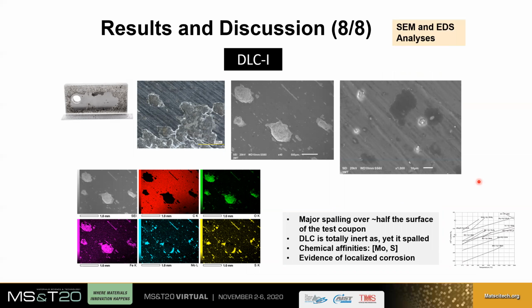Now let's look at the DLC coating. Remember, based on the general overview seen a few slides ago, this is where we had some of the worst corrosion rates. So what do we see? Here's a coupon. We see that this coupon does not look black, which is the normal color of DLC. It has become, once again, stainless steel looking. So we can find a bit of DLC perhaps here, but essentially it's gone everywhere. When we look at the optical microscope, we can see a bit of DLC and we can see the bare materials around it. Same in the SEM. And when you go into the EDS at high magnification, we can recognize through the carbon mapping where the DLC is, and everywhere else, essentially, this is the bare material.